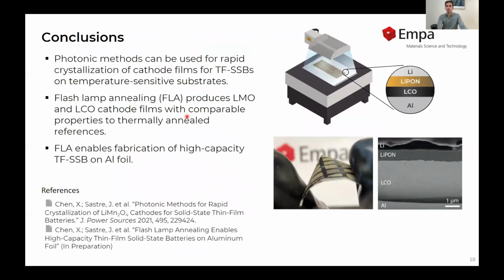And with this, I would like to conclude my talk. We investigated photonic methods as an alternative for crystallization of cathode films in thin film solid-state batteries. We demonstrated that flash lamp annealing can produce LMO and LCO cathode films with properties comparable to the thermally annealed ones. And by using this FLA method, we can produce thin film batteries on cheap, low-cost, flexible substrates such as aluminum foil. Here are the references if you want to learn more about our work.